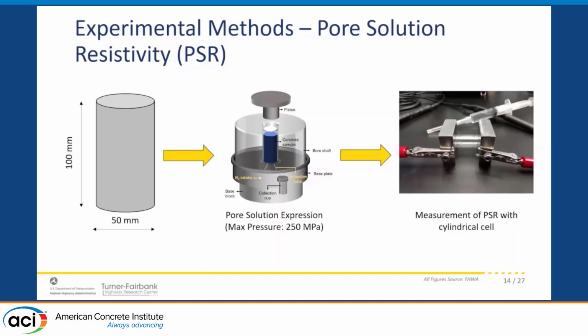You fill the cylinder in the middle with the solution, you measure the impedance, and then you convert that into resistivity or conductivity based on the geometry of the cell itself.